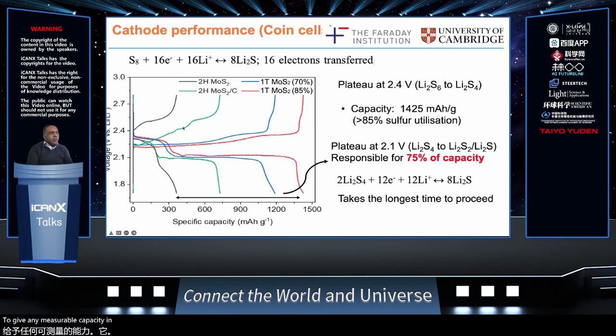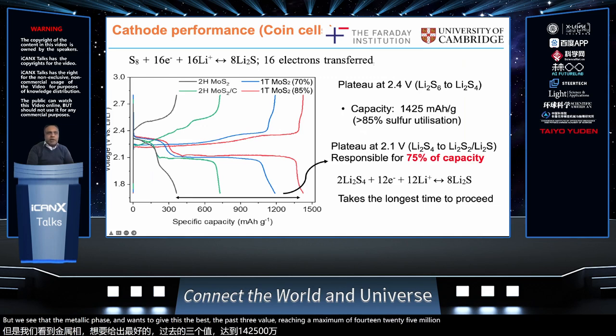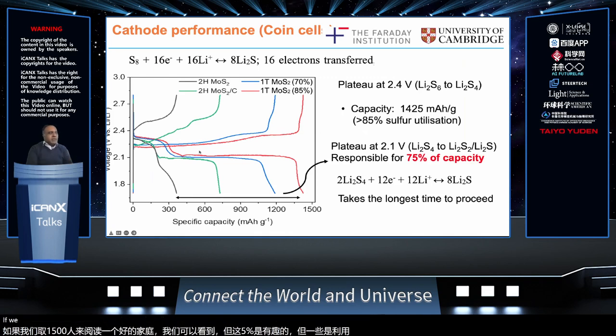If we add some carbon, things improve a little bit as indicated by this green curve. But we see that the metallic phase MoS2 gives us the best capacity values, reaching a maximum of 1425 milliamp hour per gram. And if we take 1600 to be our theoretical capacity, we can see that that's responsible for 85% of sulfur utilization.